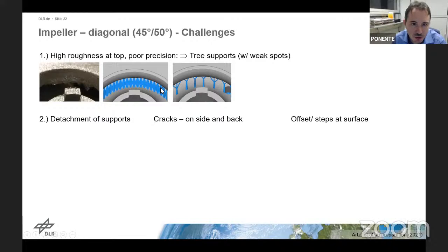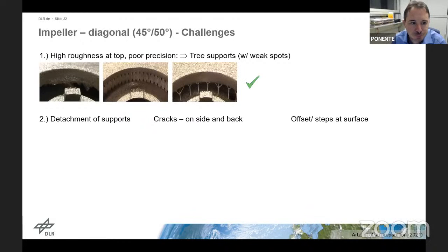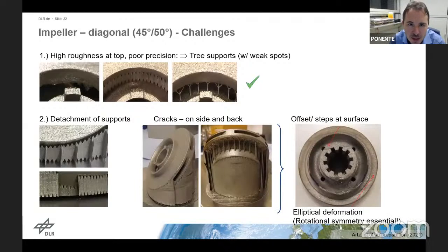We had different kinds of internal supports that we used here. In the end, we ended up with these 3 supports shown in the 3rd picture. These 3 supports are rather easily removed and they don't leave traces on the part itself, which is very nice. That worked nicely.